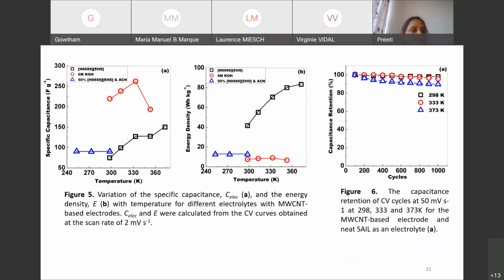Here we can see the comparison of the specific capacitance for the three studied systems: 6 molar KOH, the binary mixture of ionic liquid with acetonitrile, and the neat ionic liquid. And we can see here the specific capacitance values are very high for aqueous electrolytes as compared to the binary mixture of ionic liquid and the neat ionic liquid in the whole range of temperature. This might be because in the aqueous electrolyte, we have smaller ions and a high concentration of ionic species, whereas for the binary mixture of the ionic liquid and the neat ionic liquid, the viscosity is very high and also the ion size is very large.